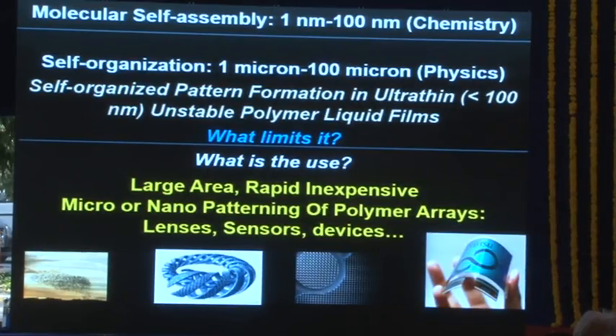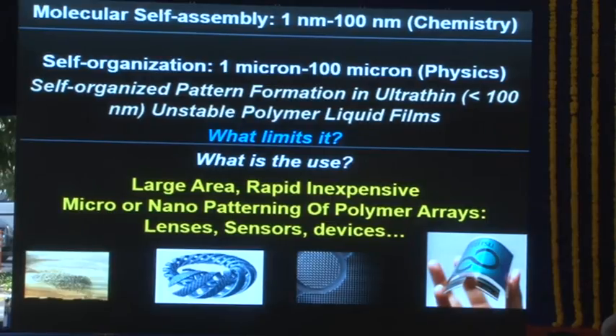Now, when you do self-organization on a very small scale, which means make a very small object, like a very thin film. Suppose you make a thin film, which is 10 nanometer thick, 5 nanometer thick, highly confined, and I will show you it is unstable. So it would change. When you do this on a very small scale, the object which comes out of it typically has dimensions of a micron. I will show that also.